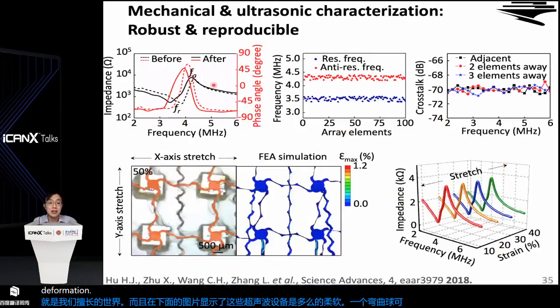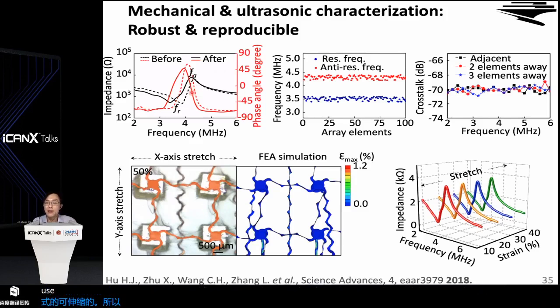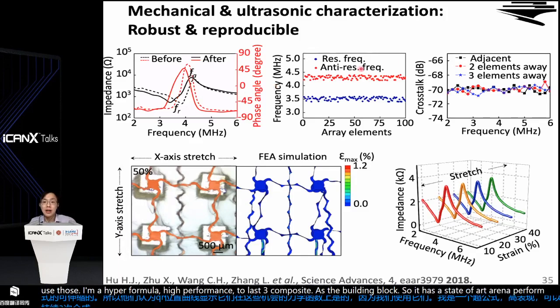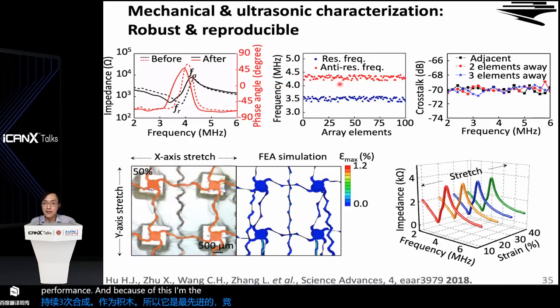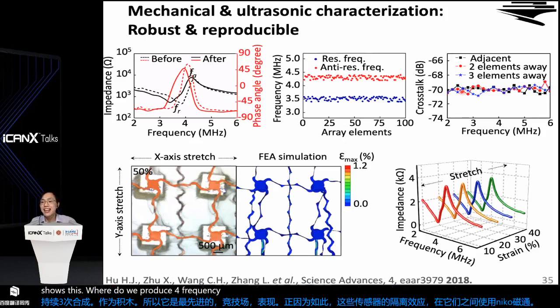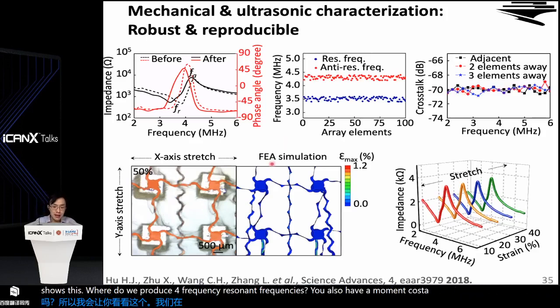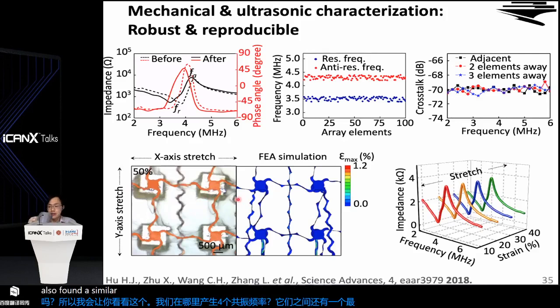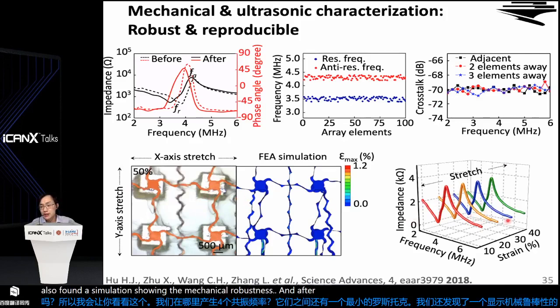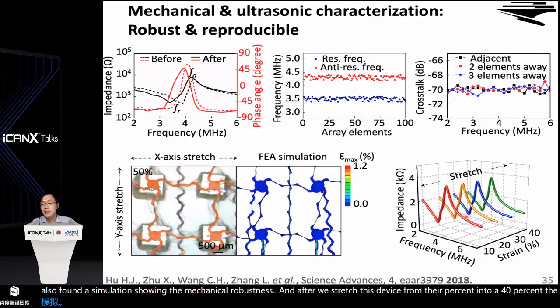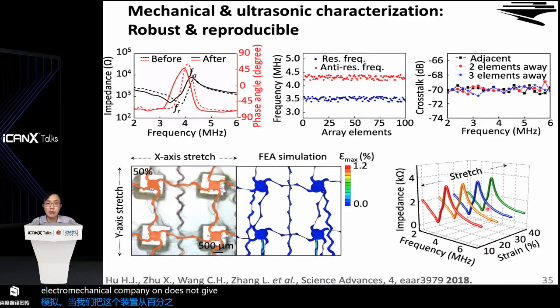So these are the characterization curves showing the electromechanical functions of these transducers. Because we use that high performance 1-3 composite as the building block, it has state-of-the-art performance. And because of the isolation effect of using this Ecoflex in between the transducers, it shows very reproducible resonant frequencies. It also has minimal crosstalk in between them. And we have also done simulation showing the mechanical robustness. After we stretch this device from 0% to 40%, the electromechanical coupling does not get affected, clearly showing the mechanical robustness of the device.